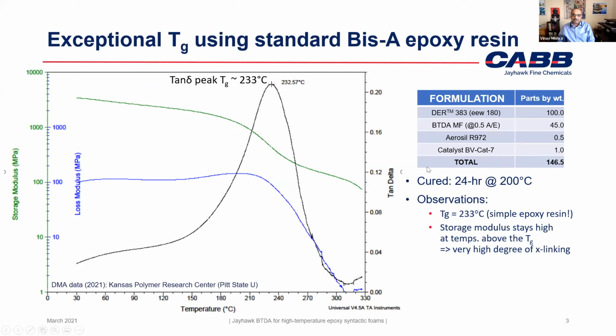And with that system, you get a very high TG. Another thing you may notice is that the storage modulus shown in the green curve starts out in a normal, as expected, glassy region. And then as it comes to the rubbery plateau after the TG, it actually stays pretty high.